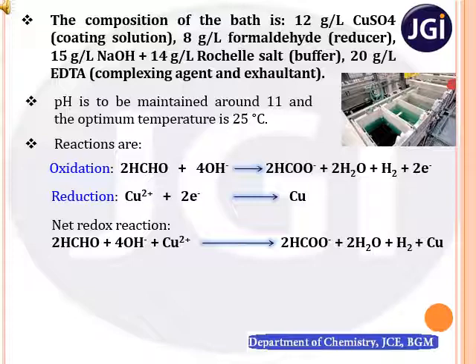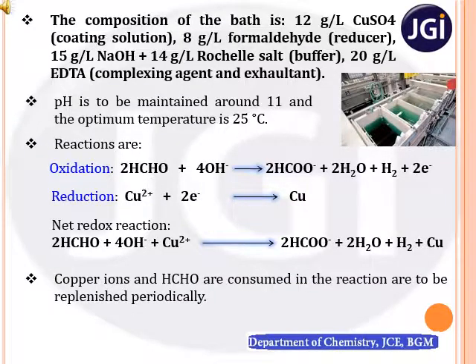Then the net redox reaction can be written as 2 moles of formaldehyde plus 4 moles of hydroxyl ion plus copper 2 plus ion gives rise to 2 HCOO minus plus 2 water molecules plus hydrogen gas plus copper metal atoms. So these copper metal atoms get deposited onto the substrate surface or the article. The copper ions and formaldehyde are consumed during the reactions and are to be replenished periodically. As you continue the plating, the copper ions get deposited, so their concentration decreases in the plating bath.